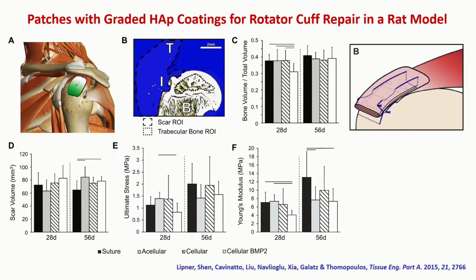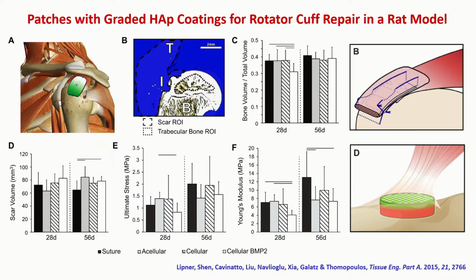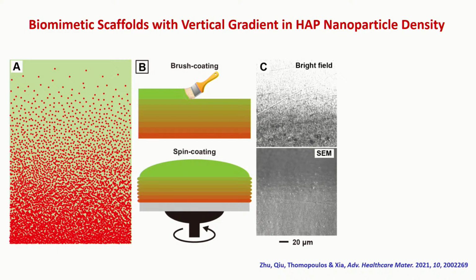So knowing this problem, we switched our direction. We are now developing a second generation of scaffold. In that case, this scaffold is going to be something like a disc. And this can be inserted between the tendon and the bone, and then you suture them together. So in this case, this scaffold will have a direct influence on the cells between the tendon and the bone. And we think this may give us better performance in terms of efficacy. So that's the second generation scaffold we are working on.